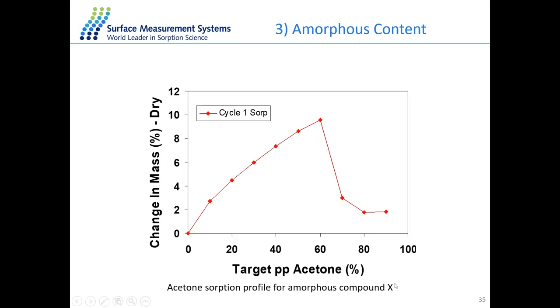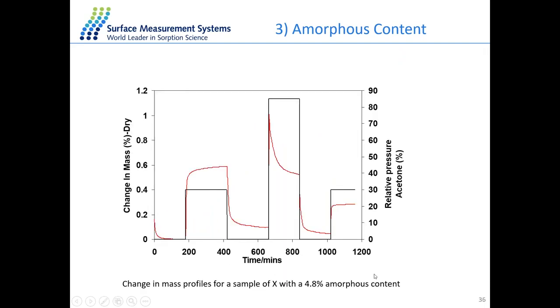In this example, looking at compound X, we're using acetone as a probe. This is a very good probe molecule because, looking at the change in mass over relative pressure of acetone, we can see that with increasing relative pressure of acetone up until 60%, we're having an uptake of our acetone. However, after this point, we see a drastic drop in mass uptake. This suggests that the probe molecule is in fact inducing crystallization. So this is a very good probe molecule to use for this compound.